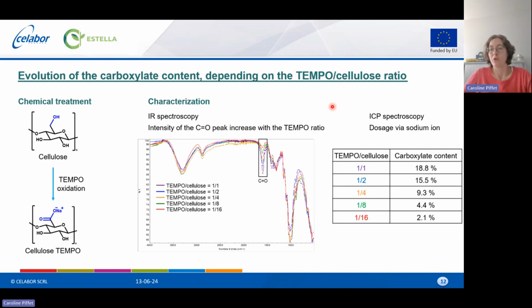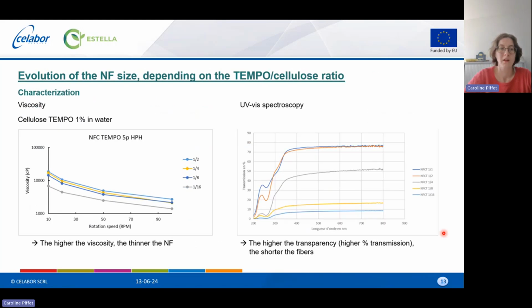And the dosage by ICP spectroscopy confirmed this qualitative observation. So with ICP spectroscopy, we saturated the carboxylate group with sodium ion, and we dosed the sodium ion, and by calculation, we obtained the corresponding functionalization ratio. And you can see that we well decreased when we decrease the TEMPO reactant concentration, starting from 20% and going down to 2%. This functionalization had, of course, some consequence on the viscosity. And so you can see that when we decrease the TEMPO ratio, we have lower viscosity.